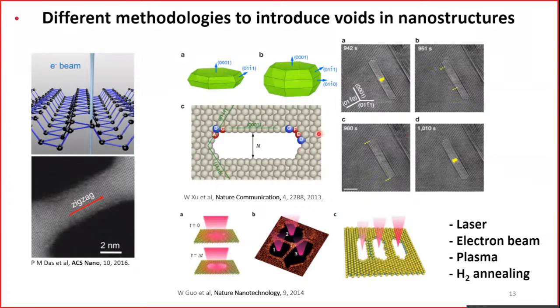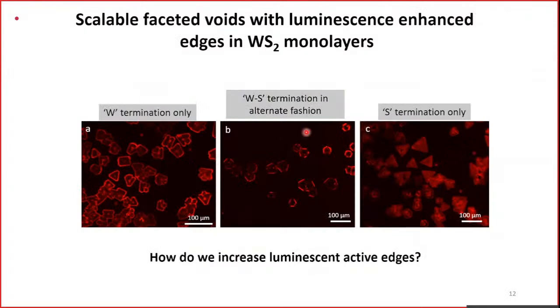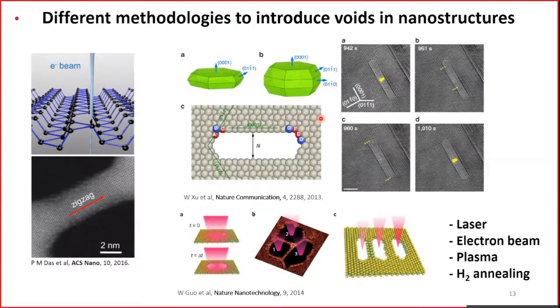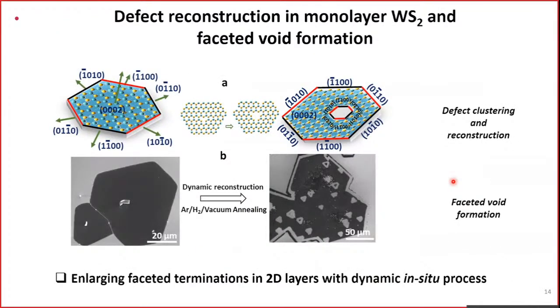There are several methods to make this kind of edges by laser, electron beam, and also plasma, and so on. There are some reports showing electron beam induced voids being created, and looking very carefully at the void termination, but they could not correlate that with the actual enhancement. But there are papers which did correlate with the enhancement. But the question is, in terms of manufacturing, making these kind of voids or producing this kind of edges by electron beam and plasma is very expensive. Can we produce them by a much simpler method?